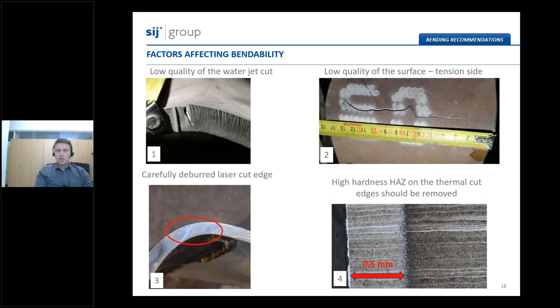Then, as you may be experienced in your workshops, sometimes during the bending process, you can get really tiny cracks on the tension side even though the suitable bending conditions were used. These small and tiny cracks can result if we have really low quality of the surface, maybe some scale imprints or something like this. And this problem increases if this low quality surface is in tension during the bending process.